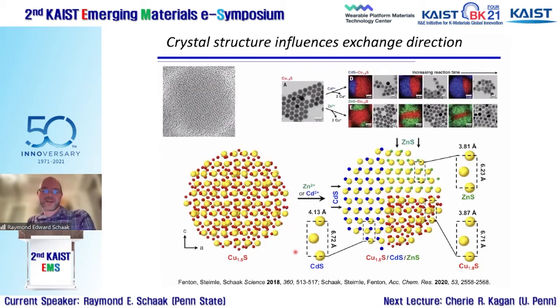But being a solid state chemist, I want to dive in a little bit more to the crystal structure issue, because this becomes a really powerful design tool for nanostructure that I don't know that in the nano world we're fully harnessing yet. So let me point this out. With the cadmium exchange, you'll notice that the orientation of the particle here, I had the interfaces being in this direction, vertical. And for the zinc sulfide, copper sulfide sandwich particles, I had the interfaces being horizontal. One could argue that was arbitrary, that was coincidental, but I don't believe in coincidences. That actually means something. That represents something at the crystal structure level.